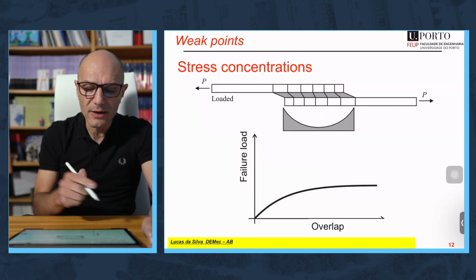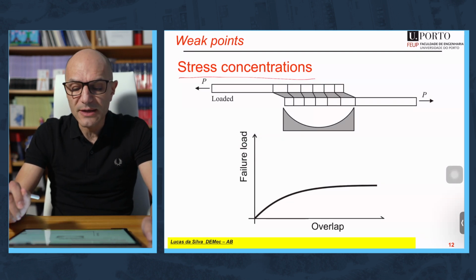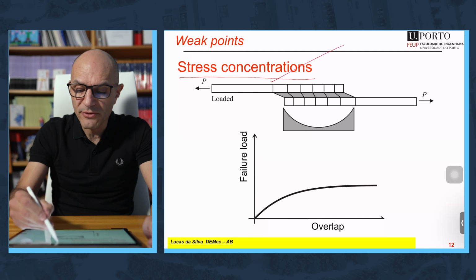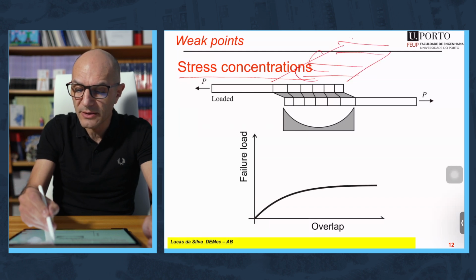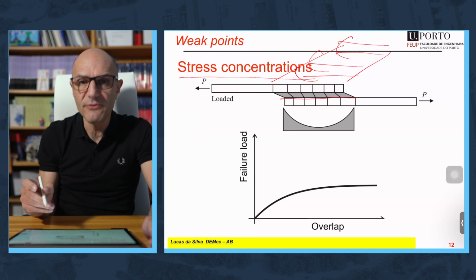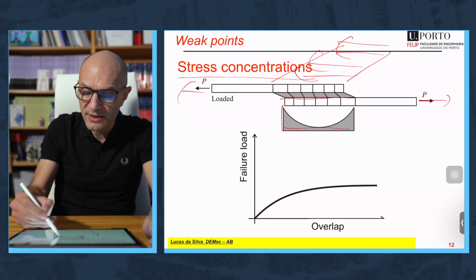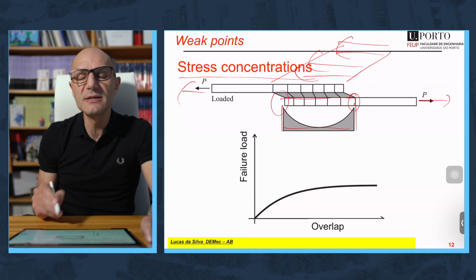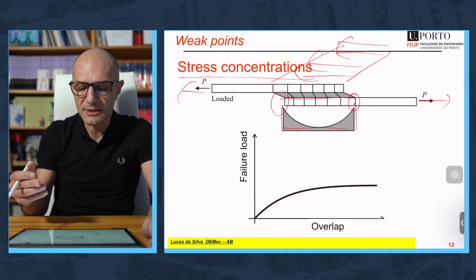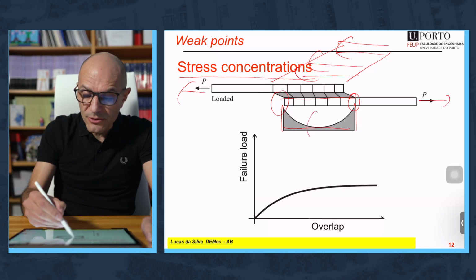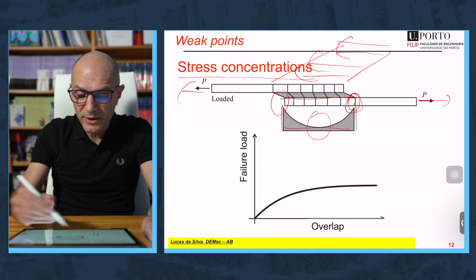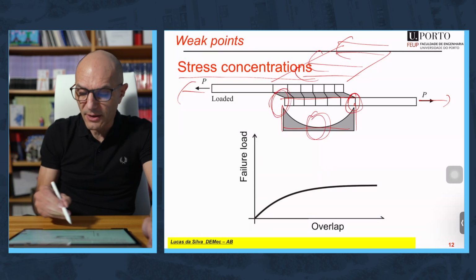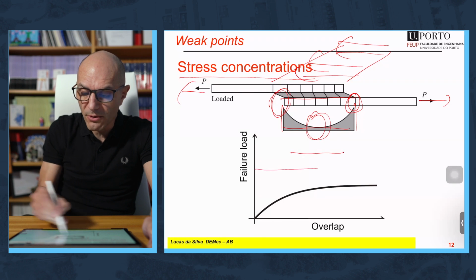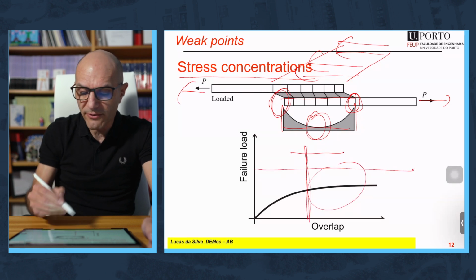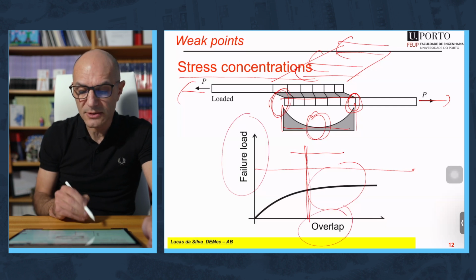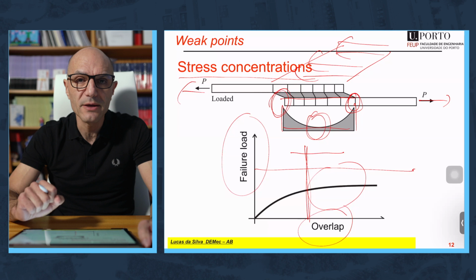Another thing that is not taken into account is stress concentrations. Well, I told you that when you load a single lap joint, the stress will be uniform. This is along the width, and it's true, I maintain what I said. But along the overlap, it's a different story. When you load a single lap joint, then you will have stress concentrations at the ends of the overlap in the adhesive. We will see this in more detail in the section of joint design. So what does that mean? It means that in fact the stress is all concentrated at the ends of the overlap. The middle is doing nothing, and it doesn't really matter if you work with a short or with a long overlap, the strength will be the same from a certain overlap, which is what is shown here in this graph, failure load versus overlap.